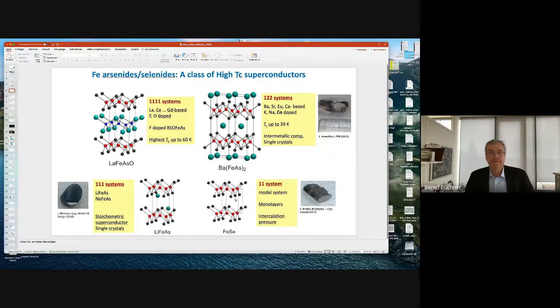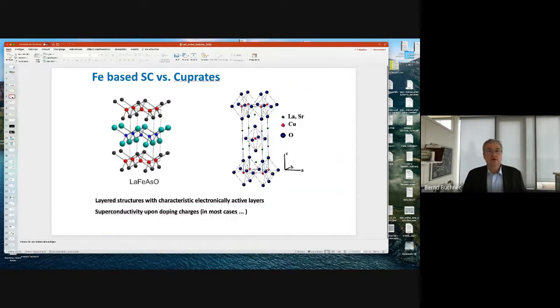So I will go back to these initial systems, which are, to my mind, very interesting, because they still have the highest TC. These are the systems we have to understand also. But they are, from the materials point of view, very complicated, because we have this oxide together with these intermetallic layers. Good. So the first idea is when you see such a layered structure, if you have active and non-active layers, that's very similar to a cuprate.